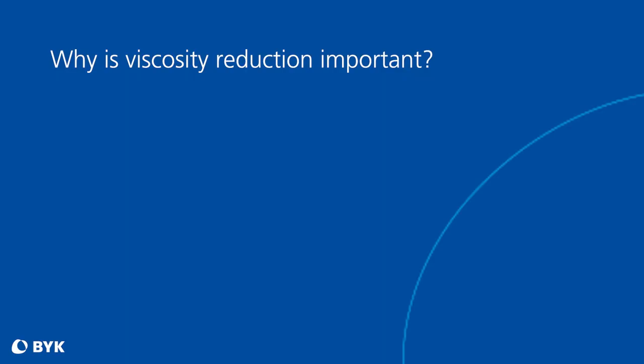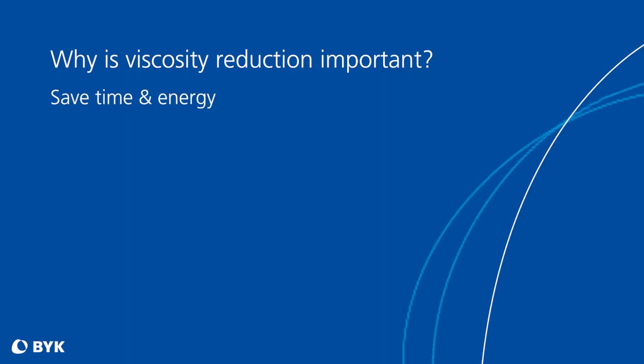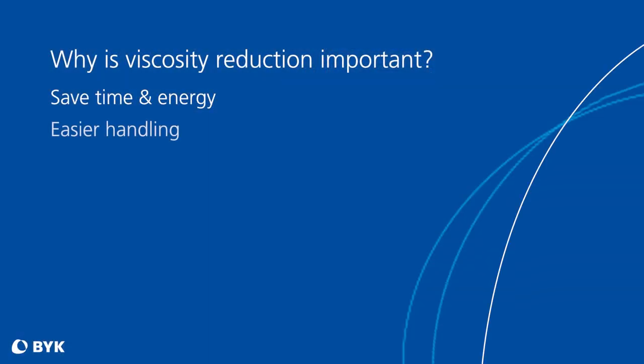And why is this important for formulators? There are a number of reasons. The first is probably more critical for manufacturing technicians. When making large-scale batches, time and energy are money. If you have the ability to lower the viscosity and potentially grind the pigments at high shear for less time, or even turn down the intensity of your equipment, then you help your company save money. The second reason is to make the grind easy to work with — it can be very challenging to transfer an extremely viscous grind into another vessel for mixing the letdown.